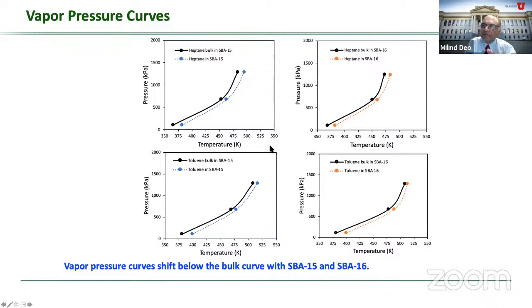Is this because the bulk actually completely envelopes the confined fluid? That's the only way we can prepare this mixture, right? When you fill these pores, you're going to fill the nanopores, but also what can be considered the bulk that's surrounding the nanopores. So does all the bulk have to go before the nano fluid evaporates? At least that's what this DSC data is telling us.